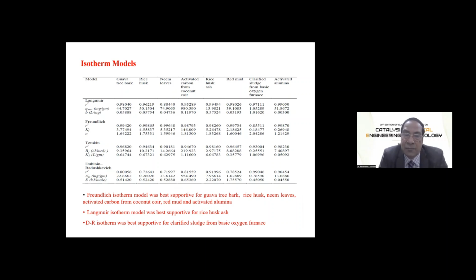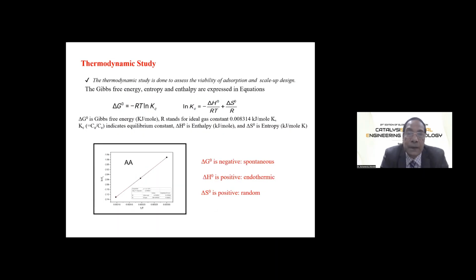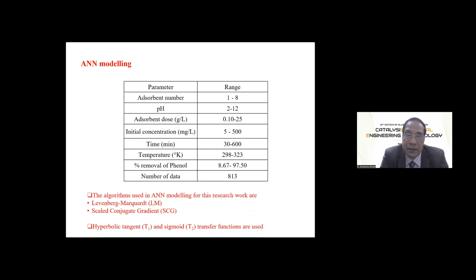And this is very important because we will be calculating our quantum of adsorbent by utilizing the best model of isotherm. Thermodynamic study we have done for delta G, that gives free energy, entropy and enthalpy, and we can get the information of the adsorption mechanism, whether it is spontaneous or not, endothermic or exothermic, and random or not.